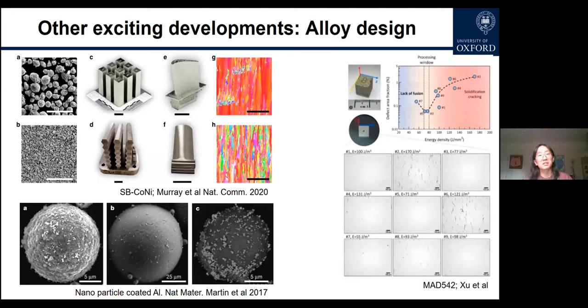Of course, it's important to address that with all the developments around the world, it's not only us doing this type of design work. Also on alloy design aspects, a lot of work has been done in Santa Barbara, for example on cobalt nickel alloys. Or if you want to increase the printability, you can try to coat the powder with some nanoparticles, which is inspired by casting technologies. And in a very cold place, such as Linköping University, people are trying to make other, even higher gamma prime content materials by similar methods. These follow a similar ideology but use different models, including DFT or first principle calculations.